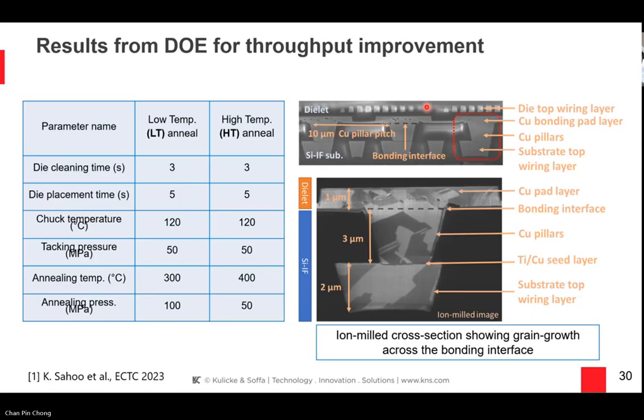And then there's a tacking pressure of about 50 megapascals, and an annealing temperature of about 300 in the low temp case and 400 in the high temp case. And the annealing pressure during this last process, which is when all the dies are now being tacked, so we're annealing all of them together right now, is about 100 megapascals or 50 megapascals. And that is done by putting a weight basically on the die.